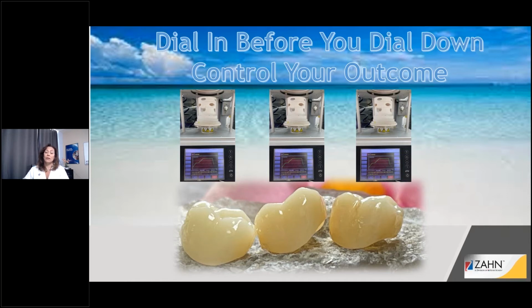One of the areas where we're kind of lacking in the laboratory is, are our furnaces calibrated? If you took the same STL file, milled it 3 times, and put them in 3 different furnaces, if your furnaces are not calibrated, you're going to get 3 different results. They could have exactly the same program. Each furnace could say that it's firing at 1500 as your high temp. But the reality is, it doesn't matter what the screen says, it matters what's happening in your furnace. And you don't know what's happening in the furnace unless you are routinely calibrating.